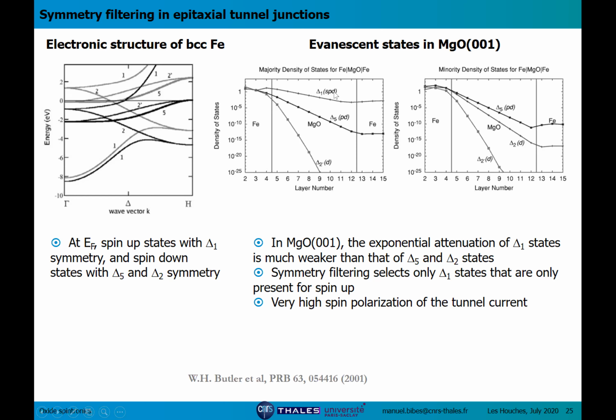Now let's have a look at MgO. In this calculation, this prediction by the group of Bill Butler, it was predicted that states with a delta 1 symmetry, or delta 5 symmetry, or delta 2 prime symmetries will be transmitted with very different exponential attenuation rates depending on the symmetry. You see, for instance, that the delta 1 states are very weakly attenuated when they cross the MgO barrier. This space here is the MgO barrier, which is maybe 7 or 8 unit cells. The delta 5 and the delta 2 prime states are much more strongly attenuated.